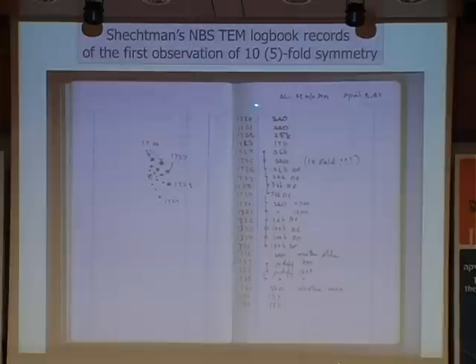And then SAD, it doesn't mean that I was sad that day, it only means that it is selected area diffraction pattern. And then 28K means magnification. This is a bright field image with 28,000 magnification, which is a low magnification for a transmission electron microscope. If you don't need very high resolution, you can magnify only a small amount like this, and so on and so forth.